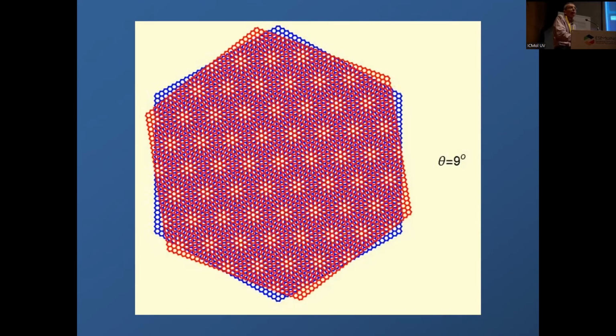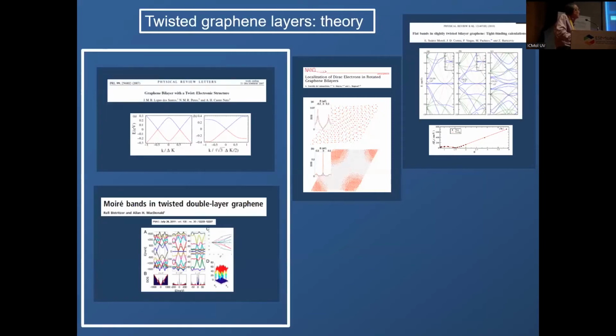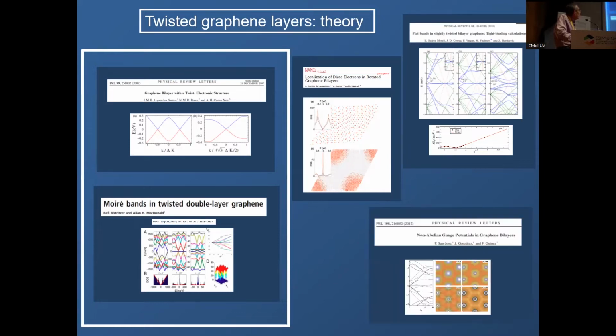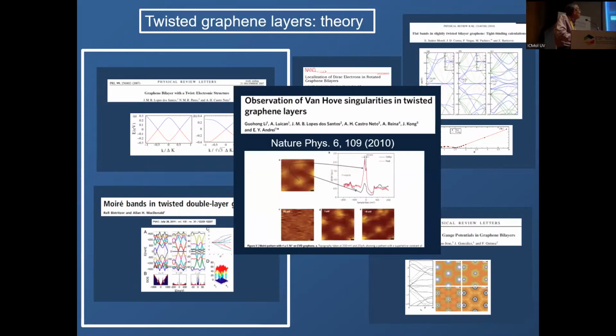So actually, Pablo Jarillo-Herrero was motivated by some interesting theory which already showed way back that there could be very narrow bands in this setup, a graphene layer rotated with respect to another graphene layer, provided that the twist angle was about 1 degree or less. There were interesting calculations which many people, including myself, thought very academic, because we thought that it was very difficult for such a system to be fabricated in nature, but it could. And there were some experiments for larger twist angles, like these ones from Ivan Brihuega's group, which showed that indeed there were peaks in the density of states, suggesting narrow bands and so on, as you approach these magic angles.